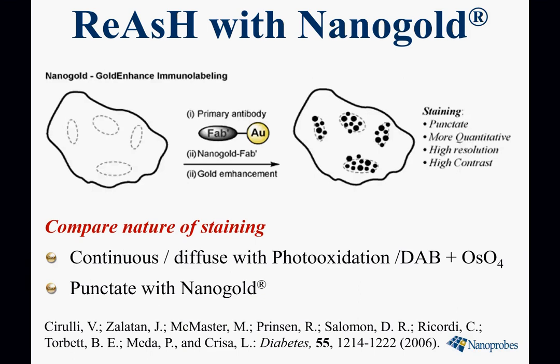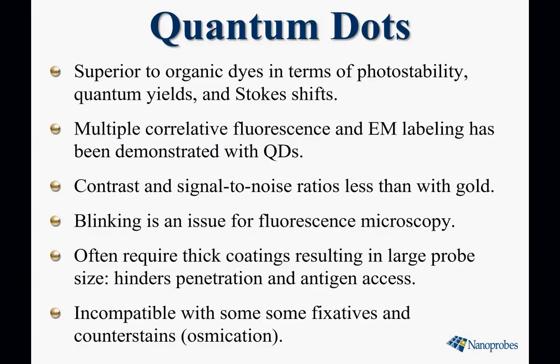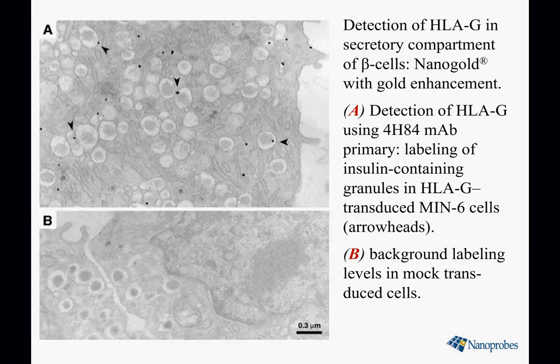And DAB with osmium has a characteristic, rather diffuse, fuzzy look to it, which makes it a very identifiable type of signal. The alternative is to use ReAsH with Nanogold. And in this case, you get a very punctate labeling with the Nanogold labeled antibody, where the individual gold particles are either visualized directly or enlarged, in this case with a process called gold enhancement, which deposits more gold onto them. And you can compare the nature of the staining, which tends to be continuous or diffuse when you use photooxidation with DAB. But with Nanogold, it's punctate, and the individual targets are identified by individual gold nanoparticles. And here, in fact, is the detection of targets with Nanogold, showing the punctate, individual, single label nature of the staining.